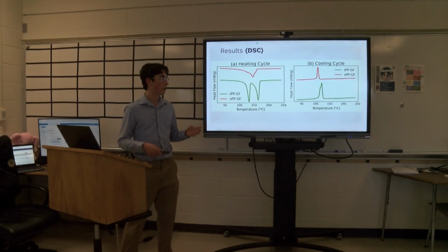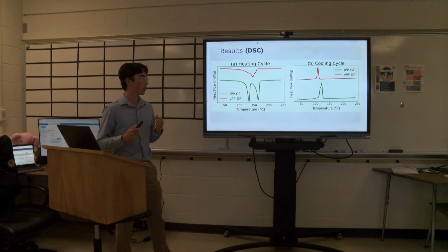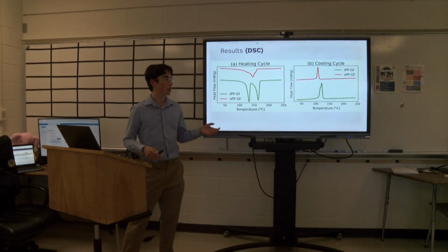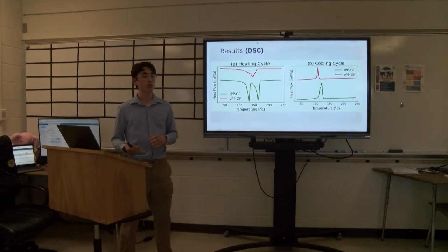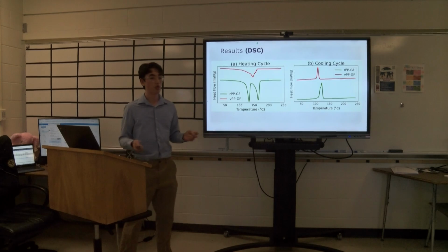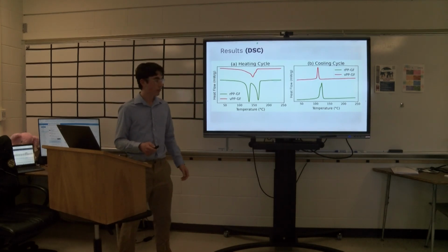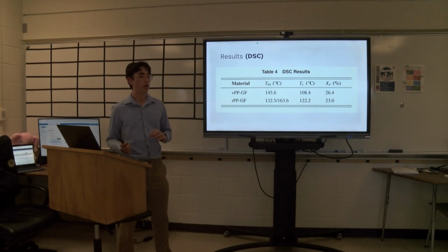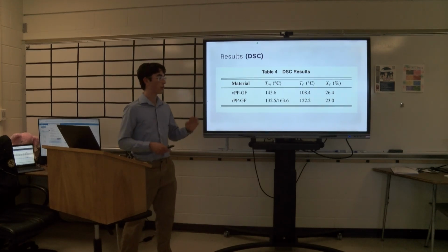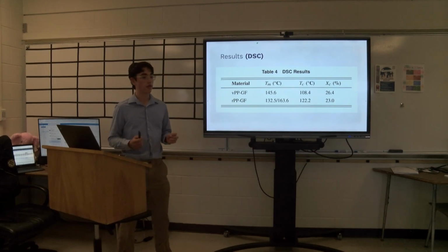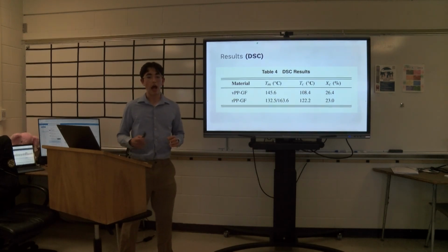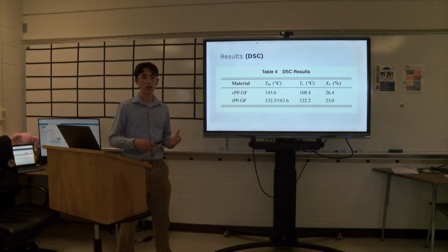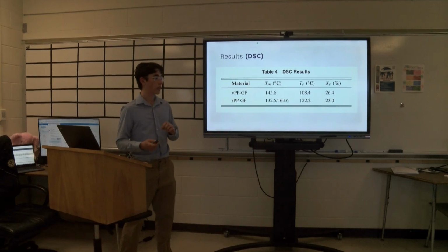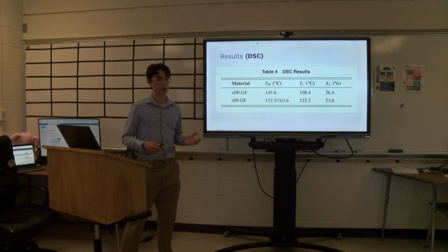Now moving on to the cooling cycle, it's also immediately apparent that the crystallization peak of the recycled material is much taller and wider. And this is because of interference between the two components' crystallization, resulting in a larger and taller peak. Now let's get into the actual numerical values. So if we look at the percent crystallinity, which is the value on the far right, it initially appears that the virgin material has a higher crystallinity. However, if you refer back to what I said earlier, there's another material present in the composite, which means that the weight percentage of polypropylene is actually lower, which resulted in a lower calculated percent crystallinity.